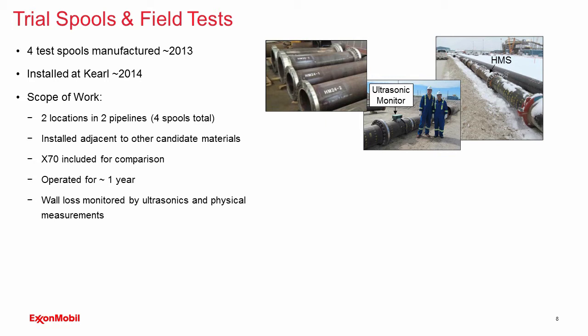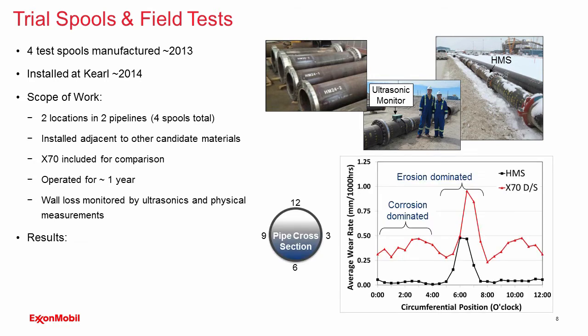They were operated for about 1 year, and the wall loss was monitored by ultrasonics, and then once they were removed, physical measurements were used to prove up the ultrasonic measurements. And so here's some of the results. On the y-axis, we have average wear rate in millimeters of material lost per 1,000 hours of service. And then the circumferential position, the o'clock position, on the x-axis, you can see 2 lines. One's high manganese steel, one is X70.